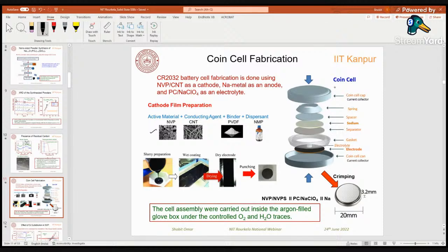So this is the coin cell fabrication assembly. One can see that this is the sodium that we have used, and this is a separator, a glass filter separator. Here you have an electrode, which we can call the working electrode, which is basically your NVP coated on the aluminum foil. We crimped it to prepare this type of coin cell, and all this assembly was done inside the glove box under controlled oxygen and H2O traces.